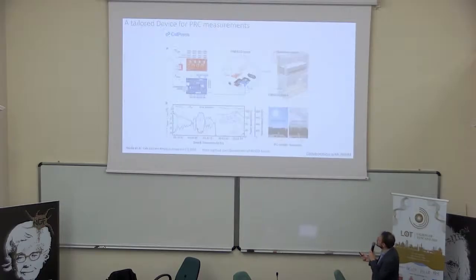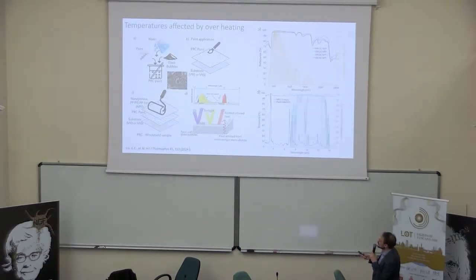This is an example of making a system like that. We made a paint with a lot of scattering glass bubbles, a particular kind of bubbles, a core glass like a sphere, in a paint, and then we cover it with this nanoporous polyethylene film that allows to reflect the UV and increase the emitted infrared heat. So this is like a combination of more or less only one material.